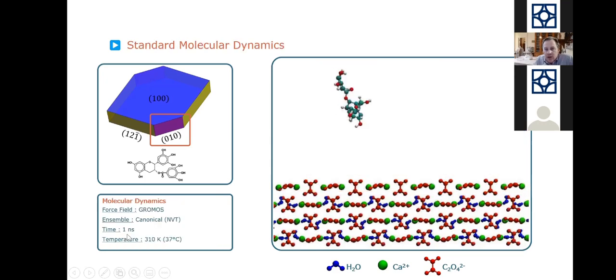So now we can go to a molecular dynamics simulation. I can show you this during the next 30 minutes, but this would not be very interesting because this is standard molecular dynamics, and this is deterministic. So we have to wait until the molecule goes through the water and adsorbs on the surface. You don't see anything here; it looks white, but in fact, you cannot see the water molecules that are present, in order to visualize the system better. So what we see is that it's maybe approaching, but it's very slow. So it's not very interesting to study, and we don't have the time to wait. So we need to find new methods, new strategies in order to obtain these geometries of the adsorbing complex.